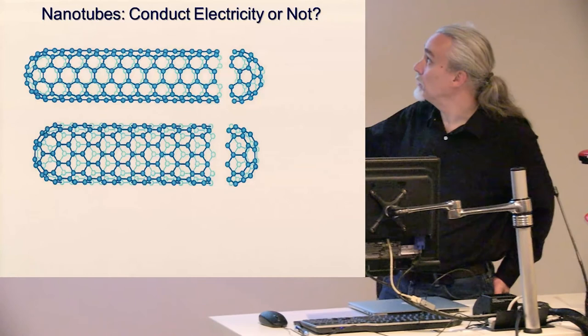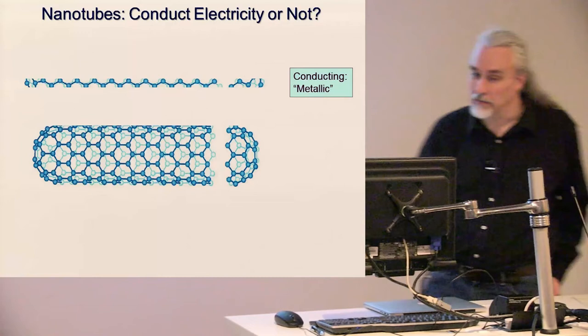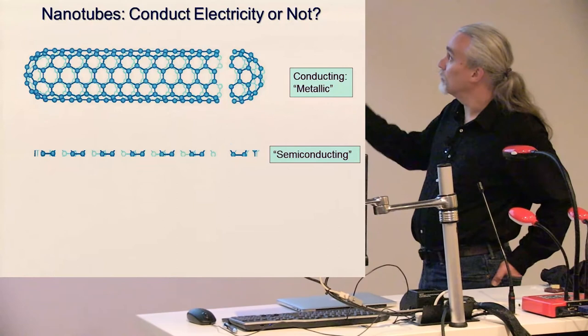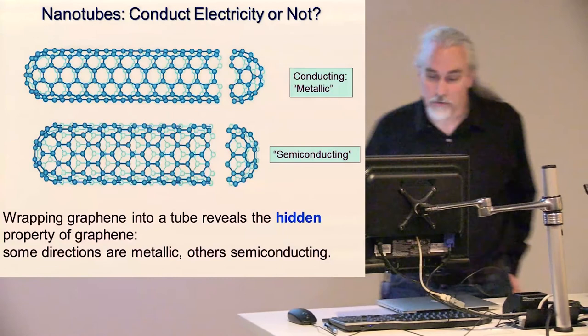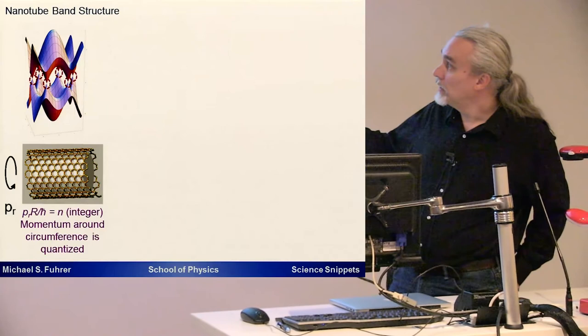It turns out that this nanotube with this zigzag chain running along its length—that's the direction that's the metallic direction in graphene—and in fact this nanotube will be metallic and it's a good conductor. This nanotube with these dimers along its length will be semiconducting, and this actually could be used to make transistors. So rolling graphene into a tube reveals this hidden property of the graphene.